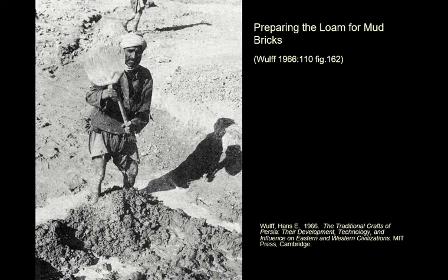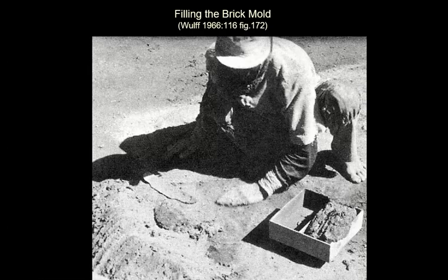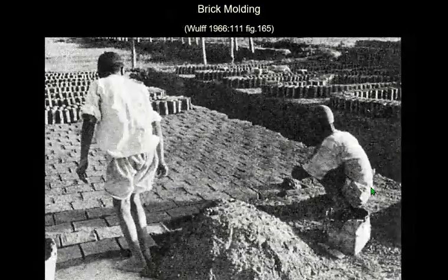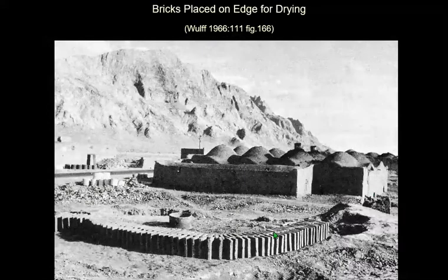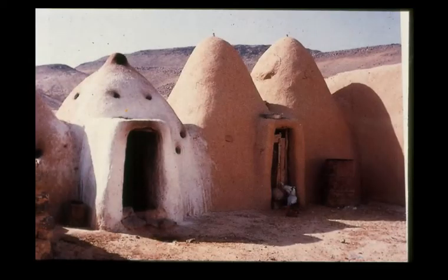For making bricks, just like for making pizé, you prepare the loam — the mud. You might want to slake the clay, make the clay wet, and sieve it. Eventually they developed the idea of having a mould — you just slap the clay into the mould, whack the mould onto the ground, and the bricks come out. So you get all of these bricks laying out in the sun to dry. These are sun-dried bricks, unfired — so if you put them in a bucket of water, they would turn back to mud. However, they're a very abundant and effective material, still used to this day.